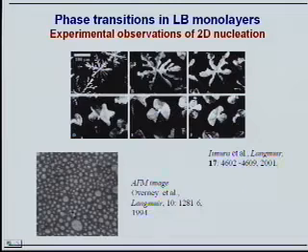You can measure the thickness by AFM if you deposit it. Now people have developed what's called Brewster angle microscopy. This is microscopy under special conditions, in polarized light, where you have very strong sensitivity of the reflected light to the conditions, the refractive index on the surface. So only polarized light and only at some specific angle allows you to actually visualize those domains here, those crystals that form in 2 dimensions on top of the surface.